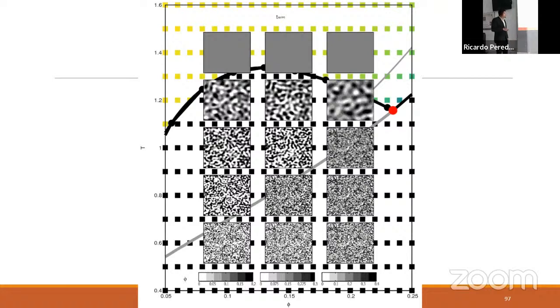In stark contrast, when observing the glass transition dynamically arrested states, which are displayed for example in these 6 states, the system freezes up pretty soon in the evolution, and we observe very small evolution from the initial configuration of our system. So this is a very visual and impactful difference that can be observed between gel and glass-like arrested states.